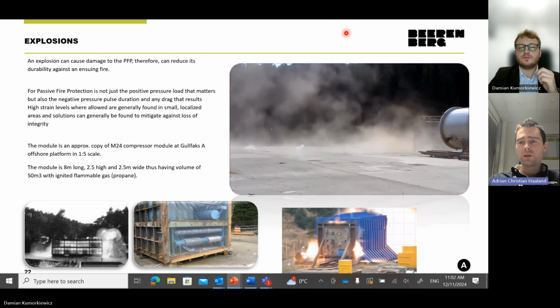And although you might think that 1 bar is not so much, I have 5 bar in my car tire or something, on a 1 square meter area, 1 bar explosion pressure is equal to 10 tons of impact load. So you can imagine having 10 elephants on top of a square meter of your system. It's quite a harsh impact, and we have tested products previously which have not been up to the spec, and if your products first start to fail, you won't even find the debris. They will be out in the forest several hundred meters away due to the extreme pressures. These are forces that can bend solid steel beams. It's not to be underestimated.